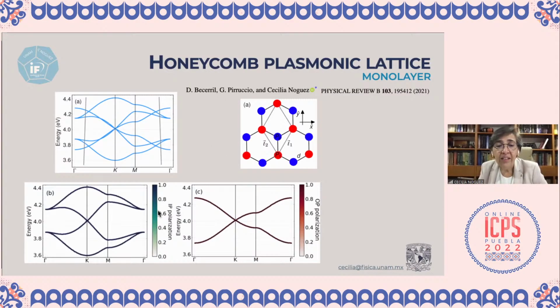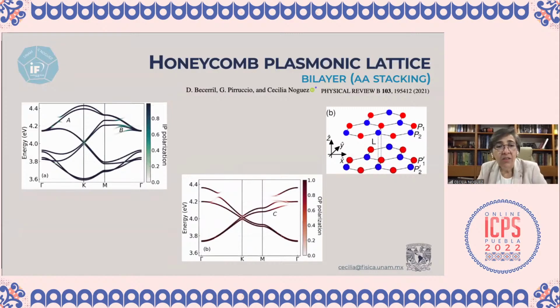You can modulate the plasmonic response of the system by using polarized light. Let's say you have in-plane polarized light or out-of-plane polarized light, and you can induce different kinds of bands in the system. That means you can modulate, let's say, the energy of the plasmonic response of the system.